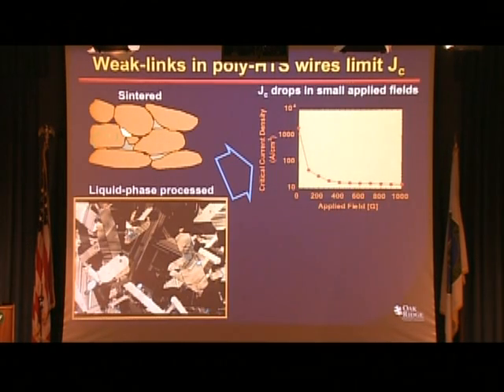Well, ceramists all around the world came up with all these fancy techniques to make these beautiful microstructures. In fact, this was once regarded as a very nice microstructure, but when you made a wire of this microstructure and passed a current through it and measured the maximum amount of current that you could carry per unit cross-section as a function of the applied magnetic field, you found that the wire could only carry about 1,000 amps per centimeter squared, and that ability dropped tremendously when you applied a small field.